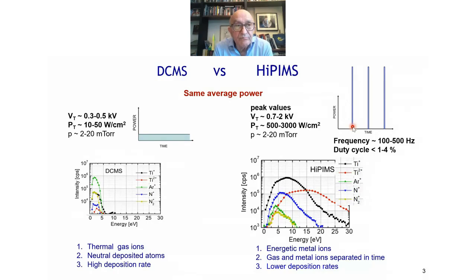They use the same target, substrate, configuration, chamber, and the same average power. But the DC, let me put the pointer here, uses a power density of 10 to 50 watts per centimeter square. It has a high deposition rate, because the sputtered gas ions, like argon ions here, are 2 to 3 orders of magnitude higher than the metal ions. So we have a combination of thermal gas ions, neutral deposited species, and a high deposition rate.